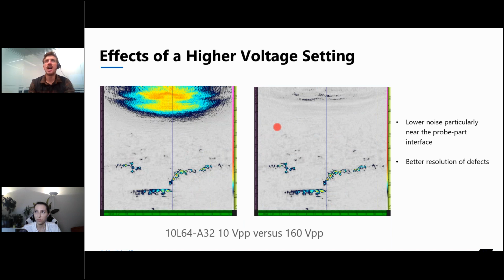The higher voltage, it's kind of counterintuitive because we're used to having more background noise in general when we increase the voltage. But here with a contact probe, it's pretty much the worst situation possible. This is with 10 volts peak to peak versus 160 volts peak to peak. And we can see that we have much less coherent noise throughout our entire scan, particularly close to the surface of our part.